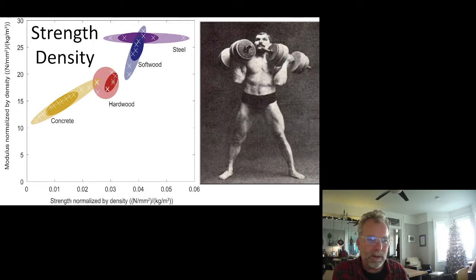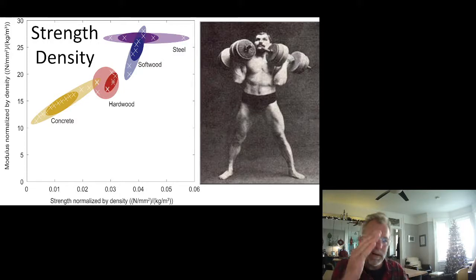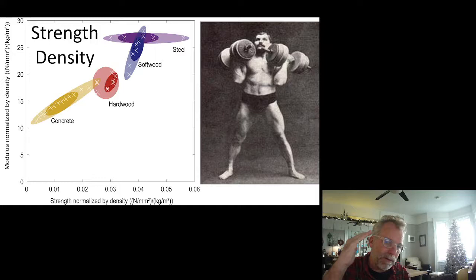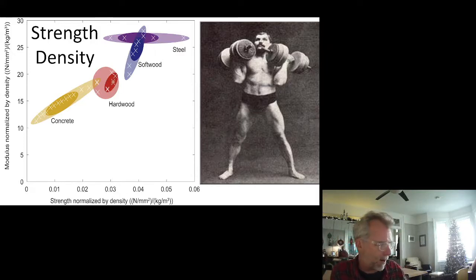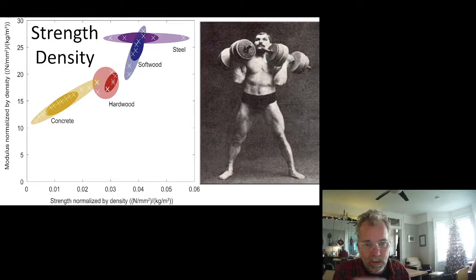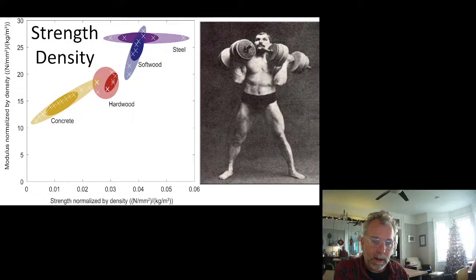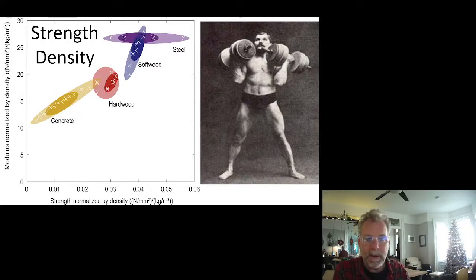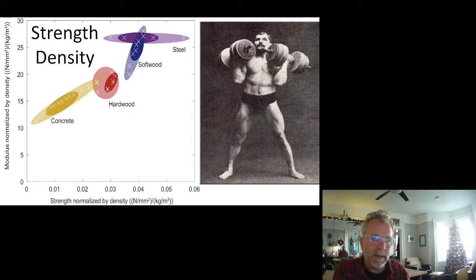Other flaws include wane — a bark inclusion where a corner of the beam was at the edge of the tree, reducing the effective size. It's the imperfections in the wood that reduce its strength, which is the reason why engineered wood is dramatically stronger than sawn lumber. In engineered wood you don't have imperfections — you cut out the bad piece, throw it out, and glue together all good pieces. Your strength is almost equal to the fiber strength.